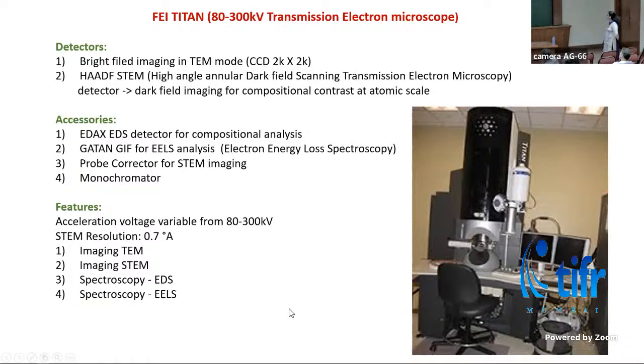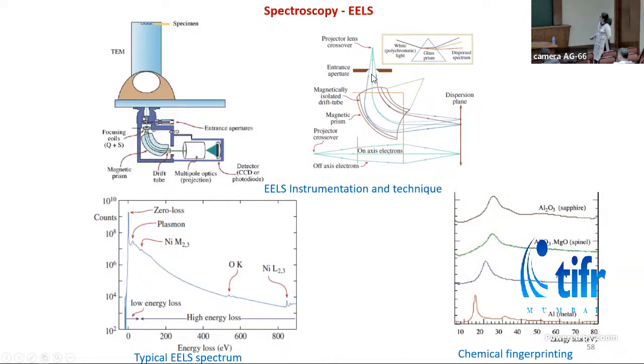It has an electron energy loss spectroscope for detecting elements present in the sample. Basically, EELS is used for detecting low Z elements, which cannot be done very efficiently using EDS. So this is the EELS spectrometer. When the electron beam passes through the sample, it loses some amount of energy. And if we can measure that energy loss, then we can identify the elements present in the sample. For example, if you have a sample and you find the electron beam exiting the sample with an energy difference of 285 eV, then we can be confident that there is carbon present in the sample, because 285 eV is the energy needed for inner shell ionization of carbon.